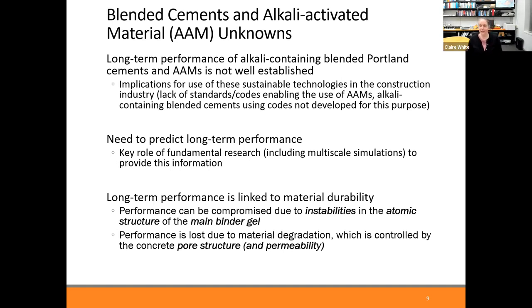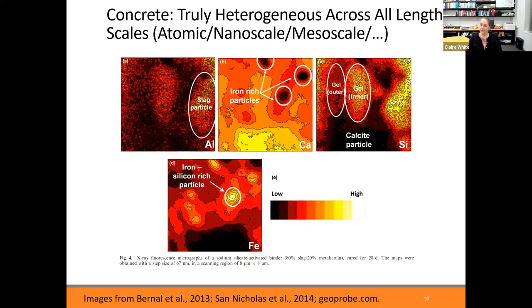There's ions as well that degrade concrete, such as chloride and sulfates. And what they do is they permeate through the pore structure of the concrete. And then they can cause phases to dissolve, or they can cause rusting of the steel, as another example. So the pore structure of concrete is very important. What I'm going to show today is very much at the atomic length scale, but it's very important to get across the fact that these systems are heterogeneous, and they're heterogeneous across length scales.